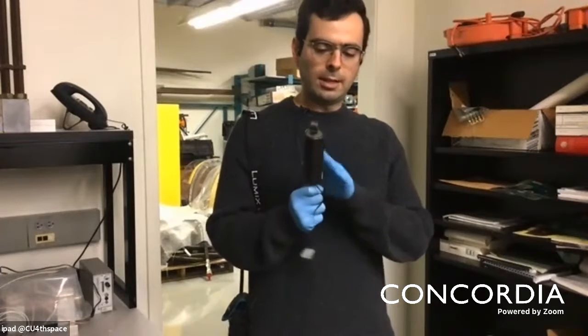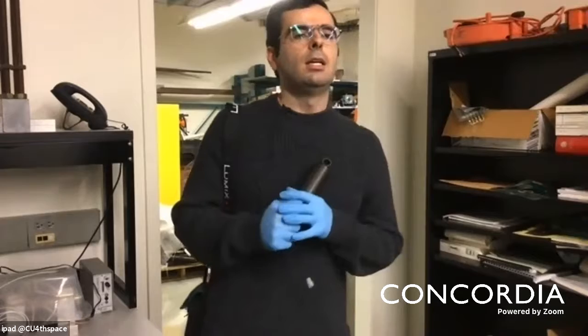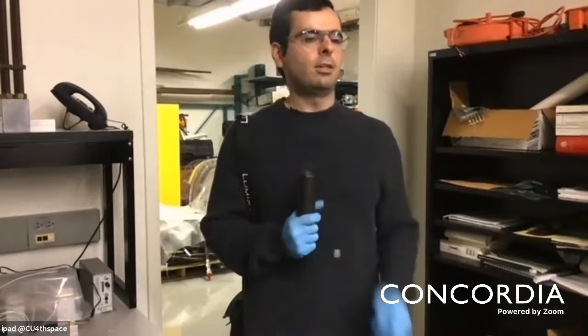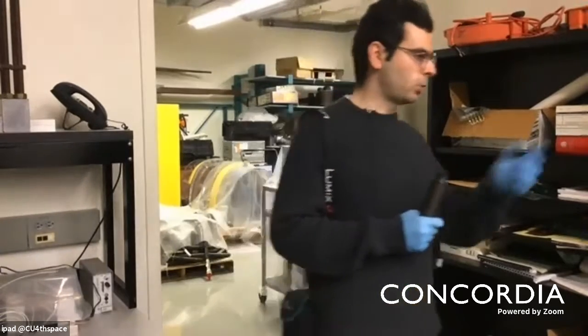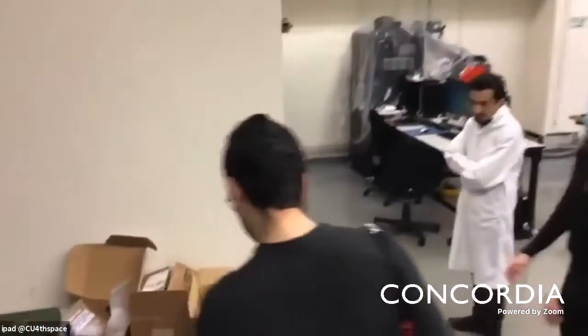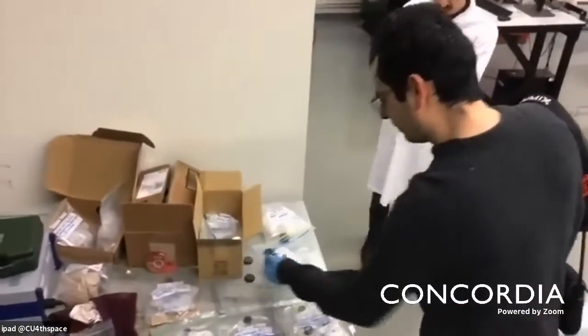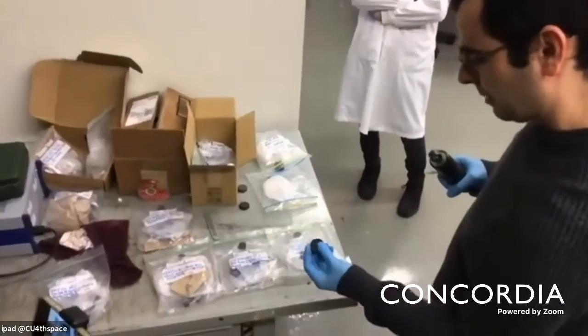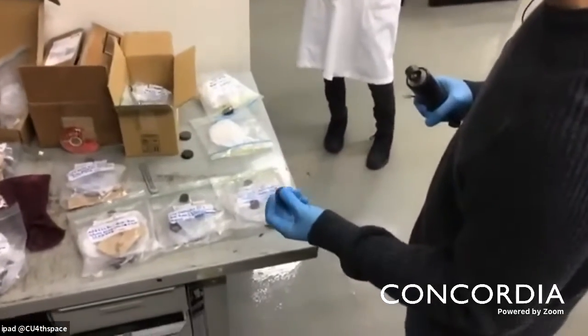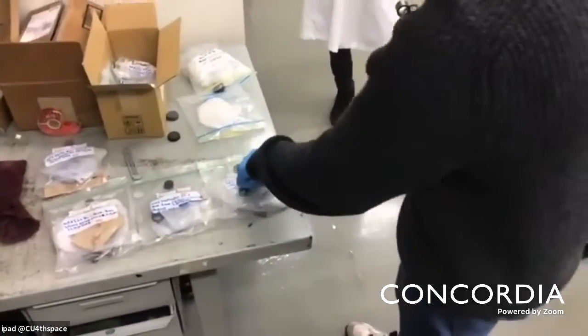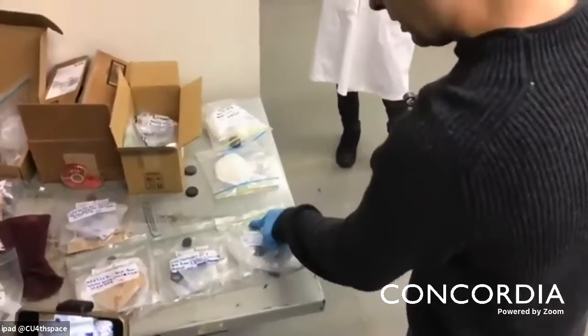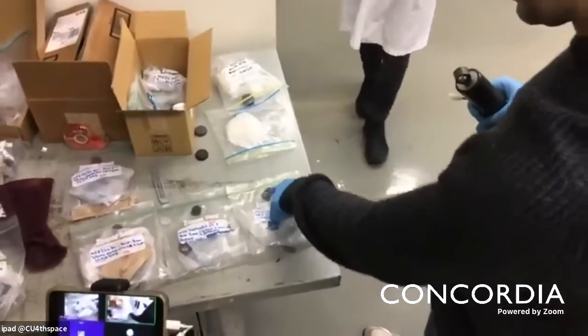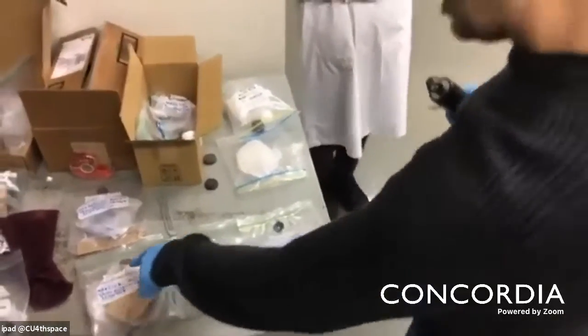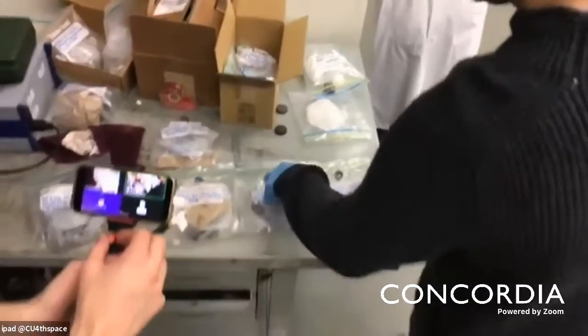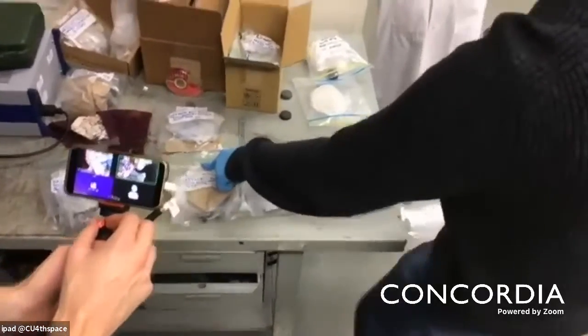Fluid inside it has an MR fluid, and my research in my PhD was on the characterization of MR elastomer material. I can show you several samples here. As I mentioned, these cylindrical MRE samples can be fabricated with different amounts of iron powder. These samples are quite soft, containing only 15% volume fraction. These are a little bit stiffer compared to this 30% volume fraction, and these are quite stiff.